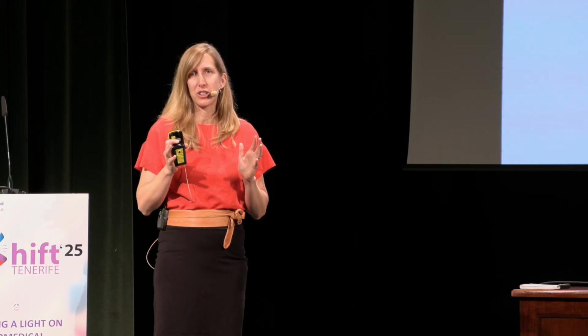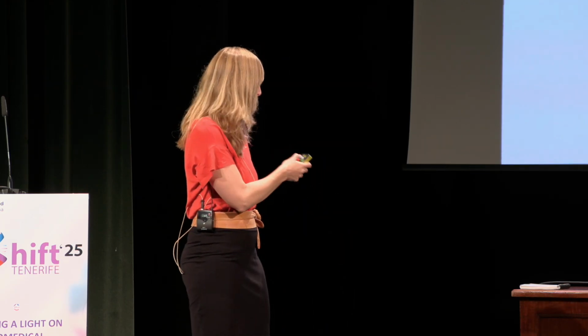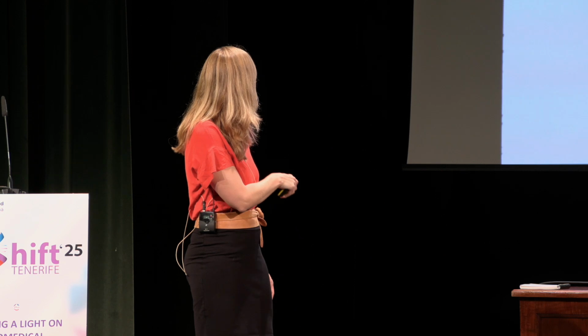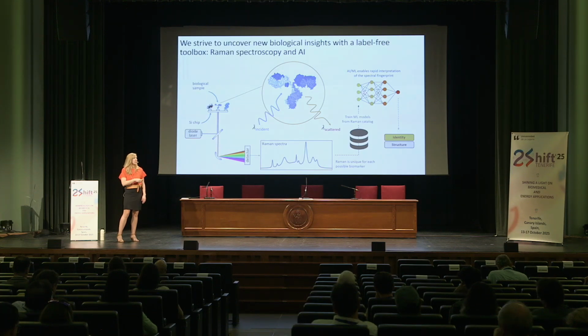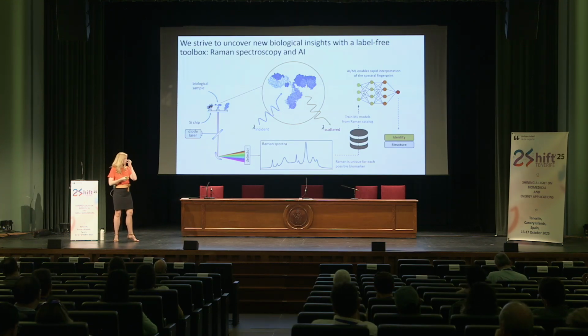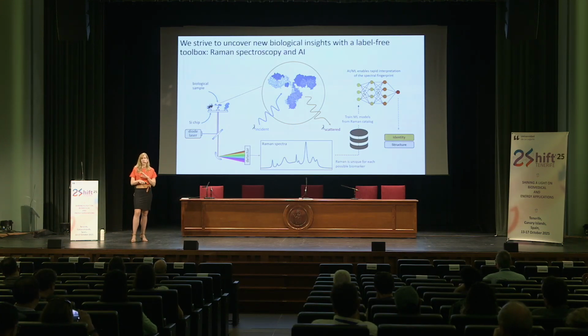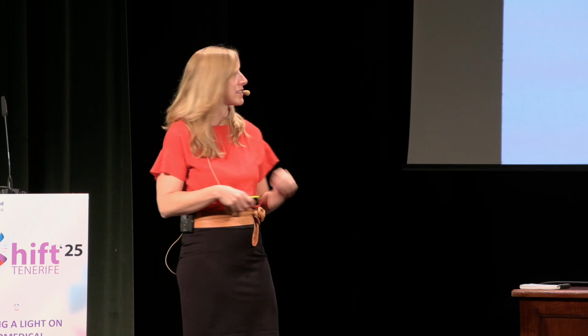What we do in the biology case is basically, again, use this vibrational spectroscopy to get label-free information about whatever biomolecules are in a particular sample. So the key gist is we come in with a monochromatic light source, usually a diode laser. And then we have our biological sample that's introduced to basically a silicon photonic chip that has millions of sensors on it. And those sensors are designed to strongly enhance Raman scattering, at least by many orders of magnitude, usually about 8 orders of magnitude. And then we're looking at this vibrational scattering signature, so this Raman spectra, which is a label-free spectra, but incredibly information-rich. So we're getting information about all of the molecular vibrations that are in a sample.